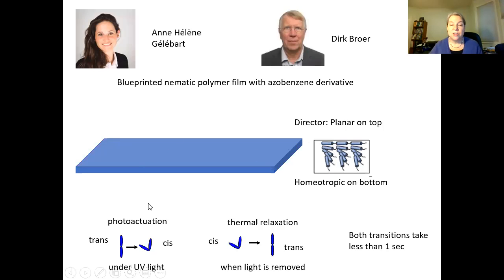And this material is actuated by light. So there is doped into the polymer this azobenzene derivative that undergoes a trans-cis isomerization when exposed to UV light, and it has a slow thermal relaxation. When the light is removed, it will go back. The chemistry of the azo dye has been adjusted here so that both transitions are relatively fast. They both take a little bit less than 1 second. So when you shine the light on it, in 1 second it's reached mechanical equilibrium, and when you take the light away, in 1 second it will relax back to where it was.